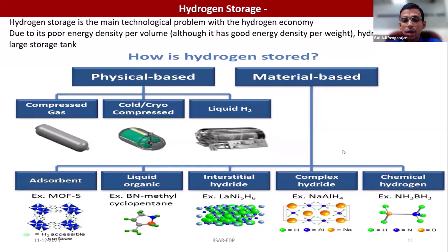So we have to go with carbon composite material, which is lightweight and impermeable to hydrogen. So the hydrogen embrittlement issue will not be there, and you can store hydrogen at elevated pressures of 300 to 700 bar. The well-known hydrogen fuel cell vehicle, the Toyota Mirai, has a carbon composite cylinder where they store hydrogen at 700 bar, so that they can handle fewer cylinders at high pressure, the overall vehicle weight comes down, and the mileage can be extended as expected.